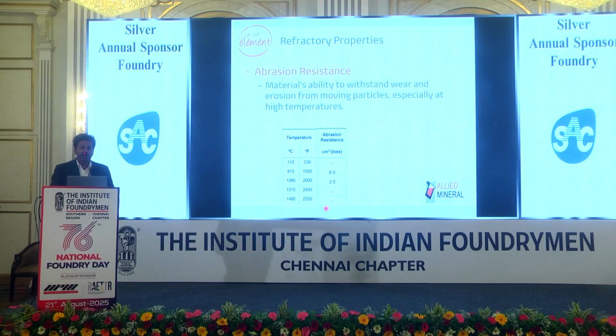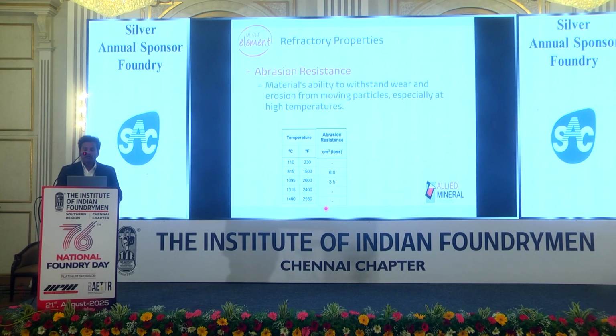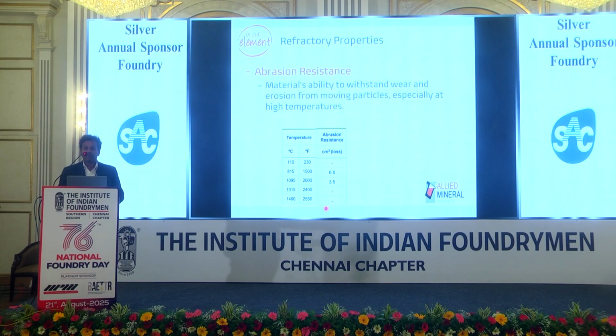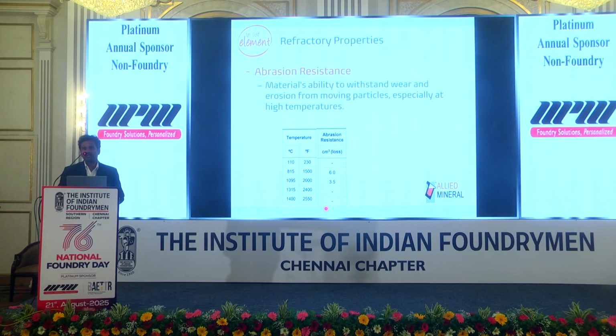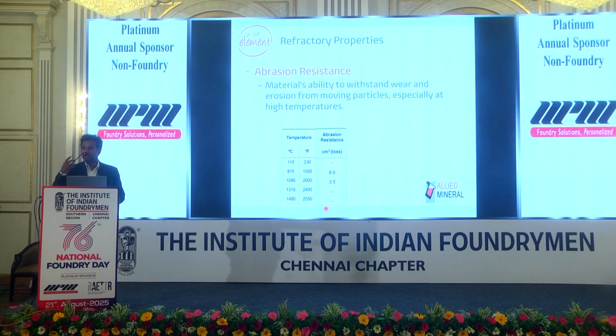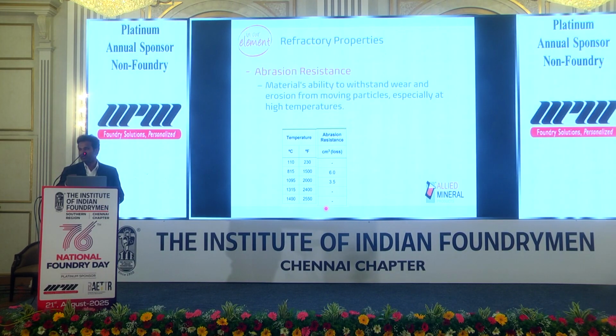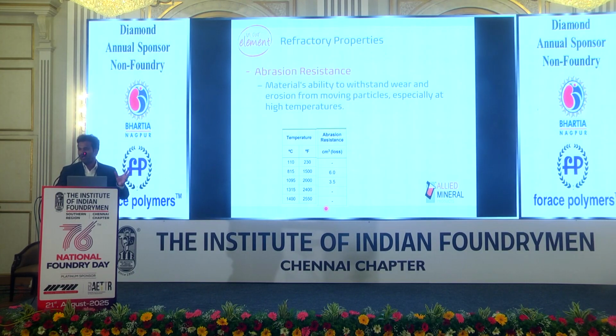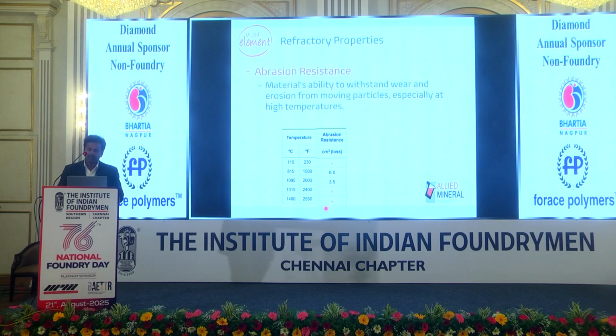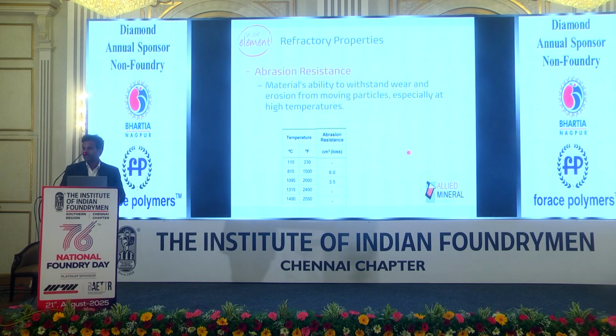The third property is abrasion resistance, the material's ability to withstand wear and erosion from moving particles, especially at high temperature. In these ladles, we generally apply a lot of abrasion to remove the slag deposited in them, and sometimes if metal has solidified, you have to apply a lot of abrasion force to remove it. So this product has to have good abrasion resistance. In general terms, the abrasion loss will be given in the data sheets. If it is less than 6, it is considered a good abrasion resistant product.